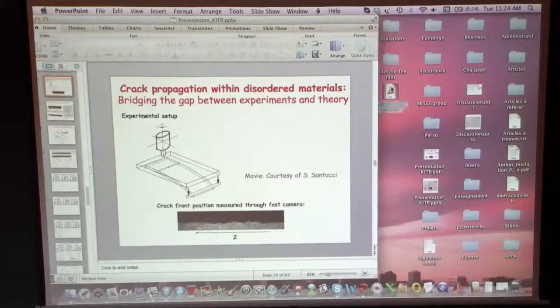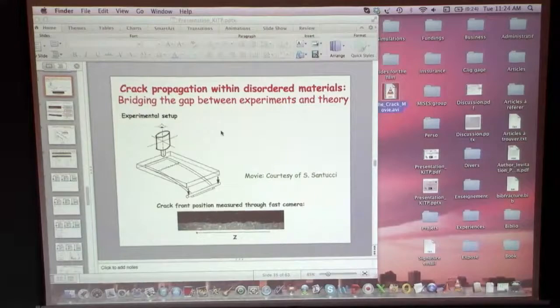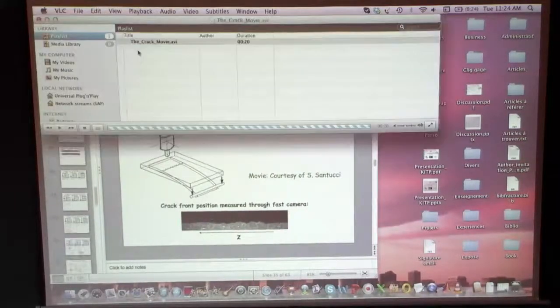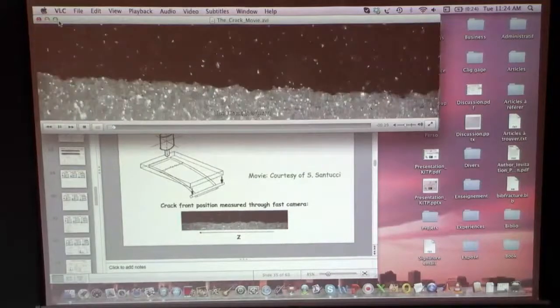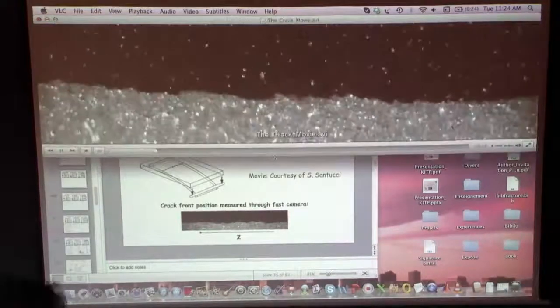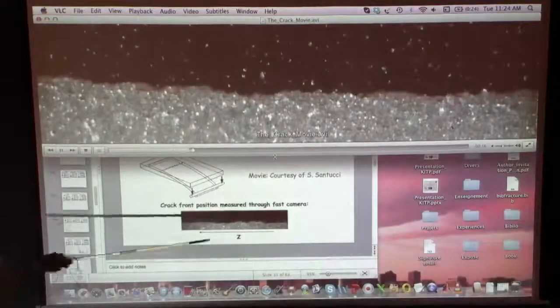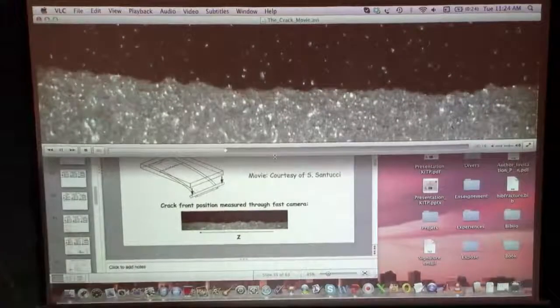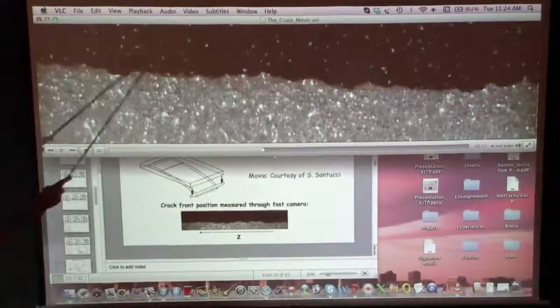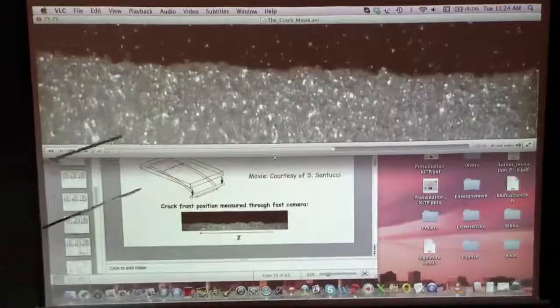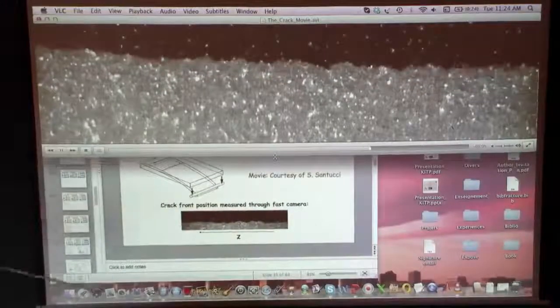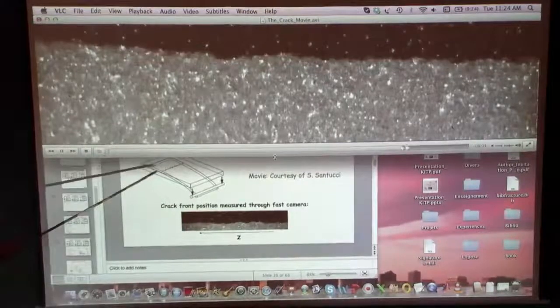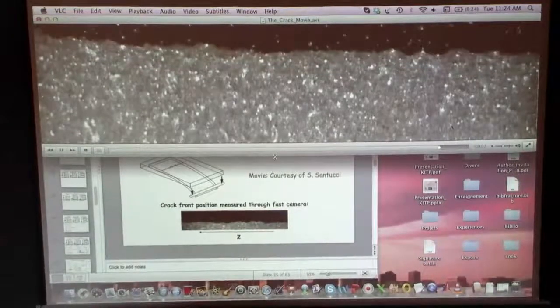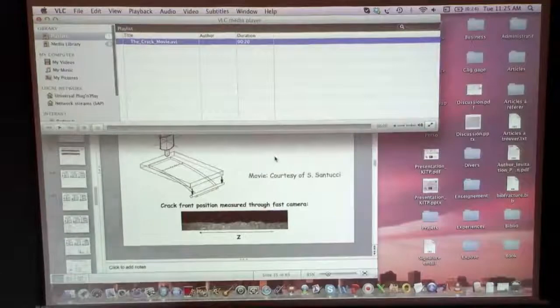This was the idea, I think, of the experiment designed by Måløy in Oslo to make a crack propagate through an interface with a random spatial distribution of defects. How this is done: they use two plates of plexiglass. They sandblast one of the plates, stick them together, and make the crack propagate.